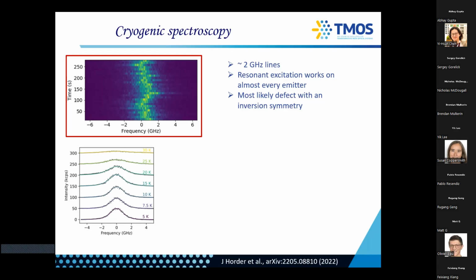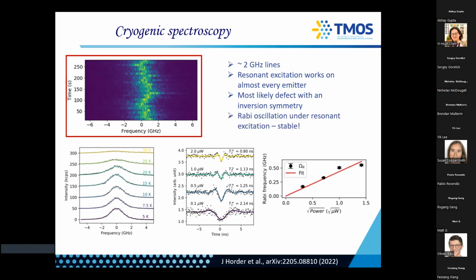And of course, when you then do a G2 measurement on resonance, you would see what's called Rabi oscillations. This is not an artifact of the measurement. This is actually a Rabi oscillation, which means that the emitter is actually coherent. And this is the first evidence that you actually have coherent emission from HBN. So if you now separate the beam, and that's what the guy is doing in the lab, delay 1 photon and let them recombine on a beam splitter, you should be able to see photon indistinguishability. So this Rabi oscillation is basically the first step towards generation of indistinguishable photons.